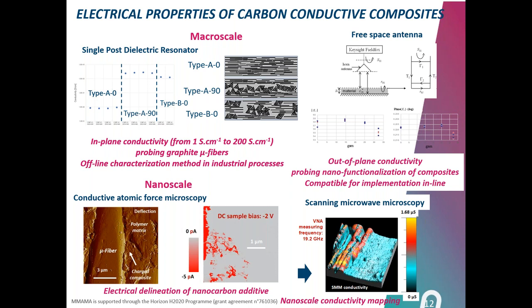At the nanoscale, as shown before, it was possible also to investigate further the way the carbon nano additive was providing contribution to the overall electrical properties by showing the way they were incorporated in the system. So on the left-hand side, you could see an AFM image where the signature of this carbon added material are sticking to microfibers. And the right-hand side, you could see similar results obtained with a scanning microwave microscopy with Keysight.